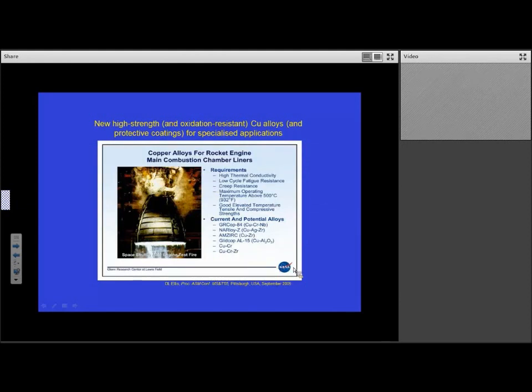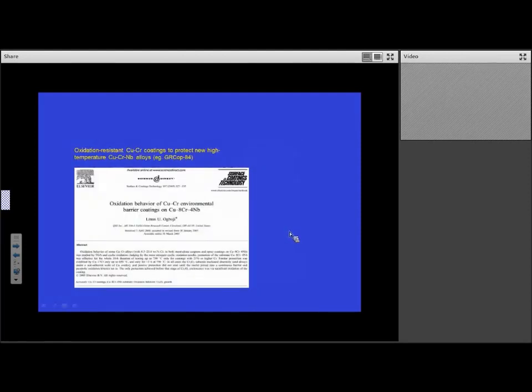In fact, I found this diagram from NASA where they're looking at some copper-based alloys. This is a copper chromium niobium with pretty remarkable high temperature properties. You just wouldn't expect some metallic-based materials like this to offer excellent performance at high temperature, but they really do. And this is a precipitation hardening alloy which gives excellent performance, again, in this kind of series of systems.